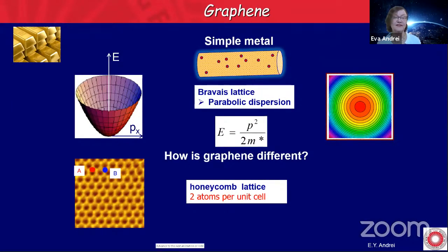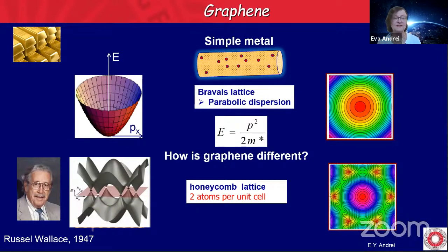And normally this will give us an insulator. However, there is an accidental degeneracy. There is a destructive interference here that closes the gap, and the band structure looks like this very strange animal here. This was already realized way back in 1947 by Russell Wallace, who calculated this band structure. So notice that the pink region here is where the Fermi energy sits. Down here, all the levels are full, and up here they're empty. These are electron levels, these are hole levels. And if it were not for these points here, we would have an insulator. But these points are where the band structure closes, and that is where things get really interesting.